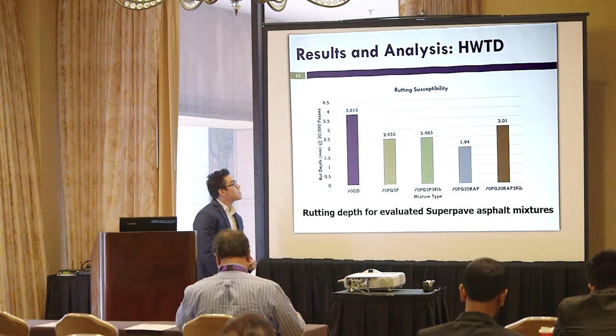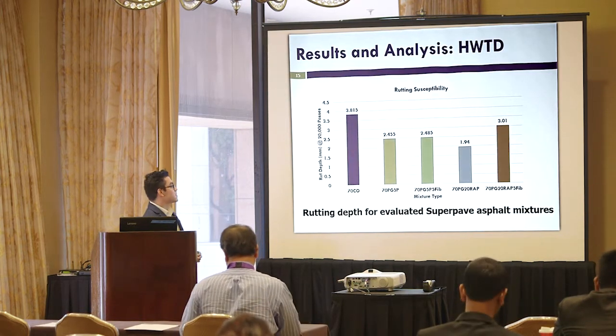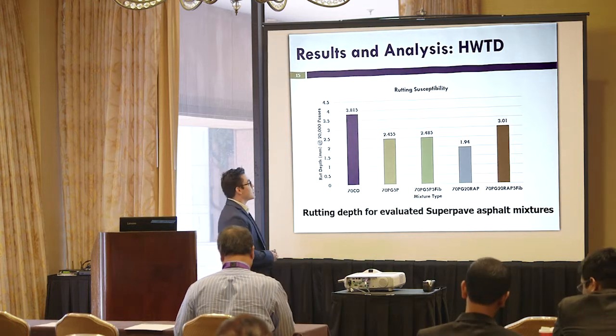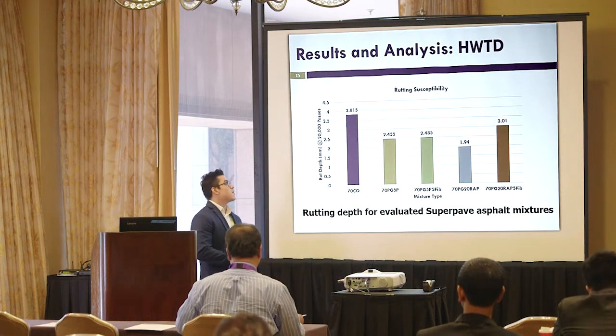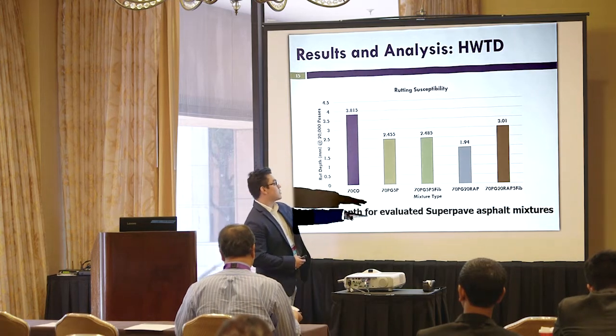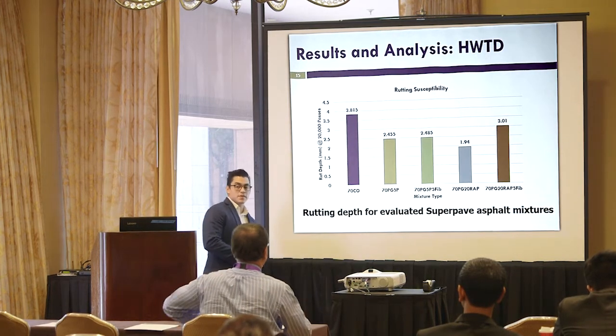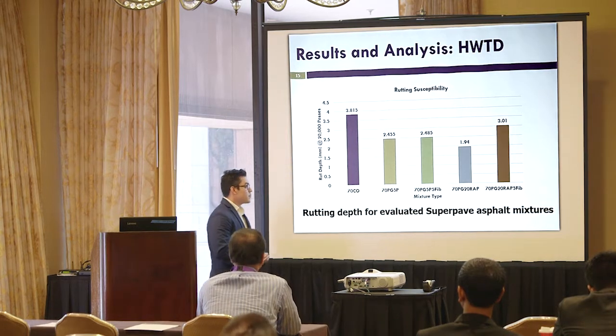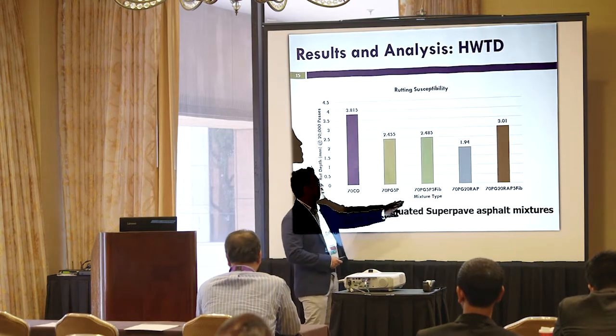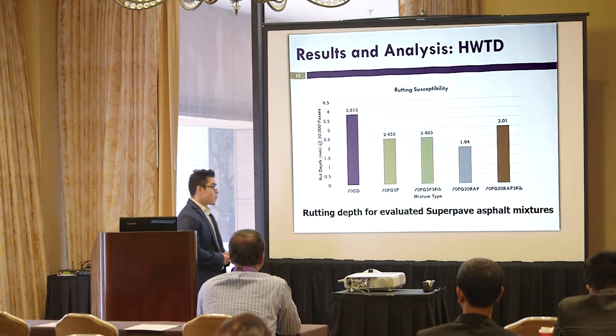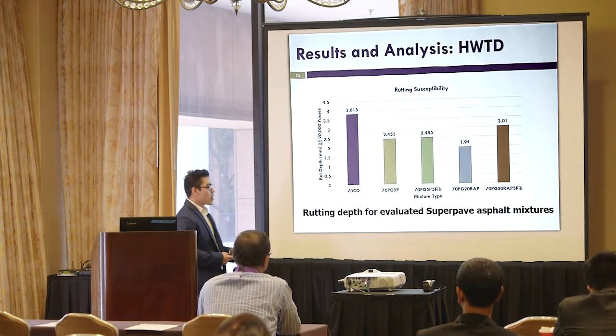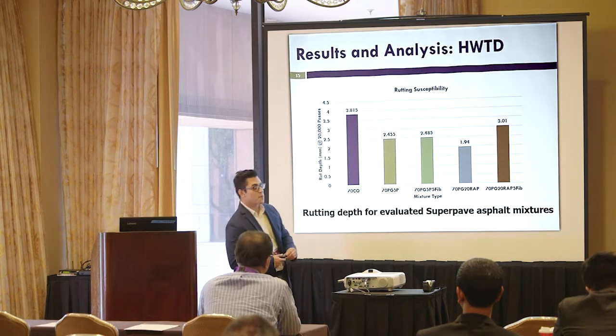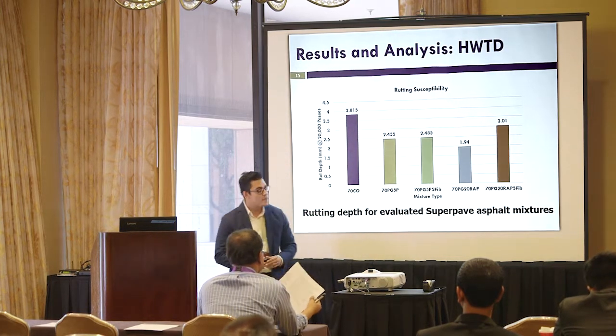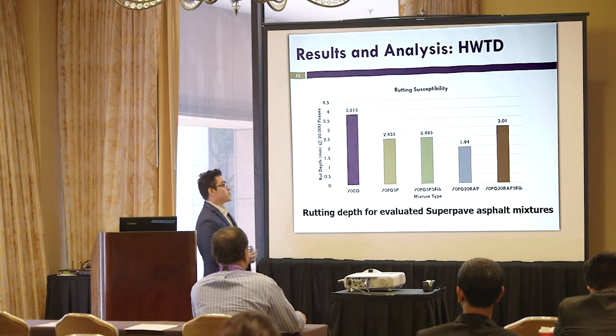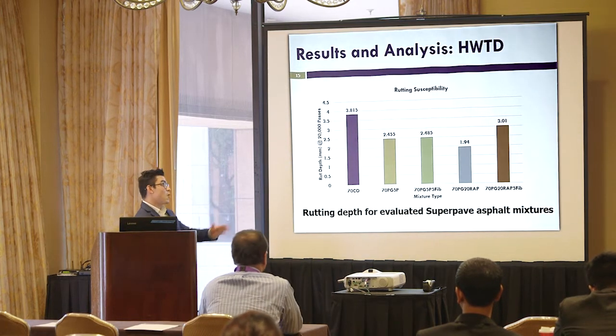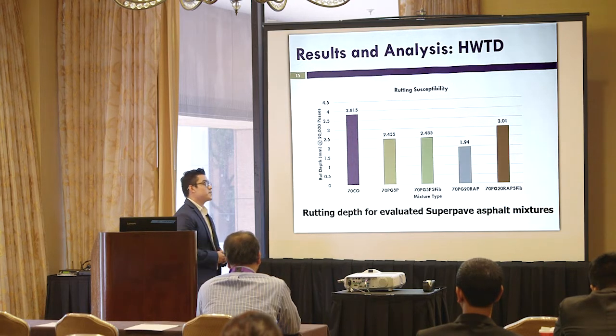For phase 2, for the Hamburg wheel tracking device, we observed the same behavior as the MSCR test, where whenever we were adding recycled materials, 5% RAS, the rut depth decreased. And whenever we add 5% fibers in the mixture with RAS, the rut depth performance was basically the same. However, whenever we add the fibers in the mixture with 20% RAP, the rut depth increased, and we were not expecting that, to be honest. However, it still performed better than the virgin mixture.